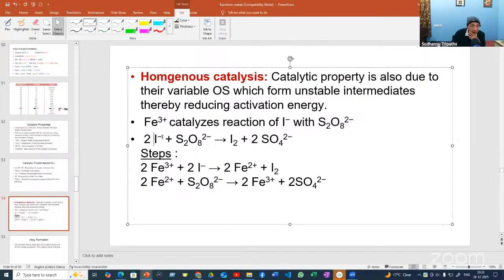For the oxidation of iodide ion to iodine by peroxydisulfate ion, it is catalyzed by ferric ion. Some ferric chloride is added. It enhances, speeds up the process. Otherwise, it becomes very, very slow. How? Because the catalyst, in step one, the catalyst ferric ion first oxidizes iodide to iodine, and itself is reduced to ferrous. And this ferrous brings about reduction of peroxydisulfate to sulfate, where oxygen in the internal peroxy linkage, the bridging peroxy linkage, was -1, and here all -2.